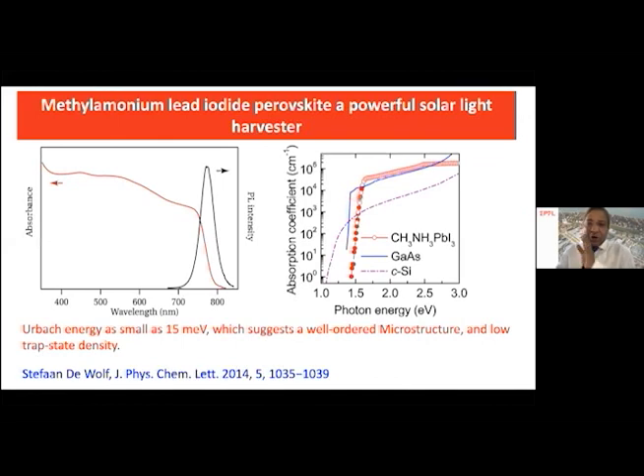So this gives you the opportunity to use these materials for a tandem configuration using silicon and the perovskite, where the perovskite absorbs the high energy photons, leaving the low energy photons to the silicon. This way you can increase your power conversion efficiency over 30% theoretically. But today, the highest power conversion efficiency of silicon perovskite solar cells is reported by Oxford PV, which is 29.5%.